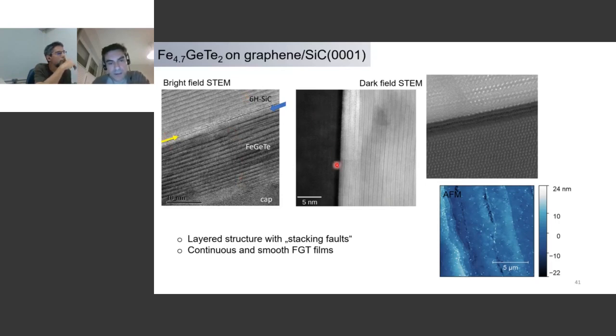Of course, it's not all perfect here. You can see in this image that although we have the layered structure, especially close to the interface, we have some rotational disorder within a very small area. You see different alignment of the FGT here.